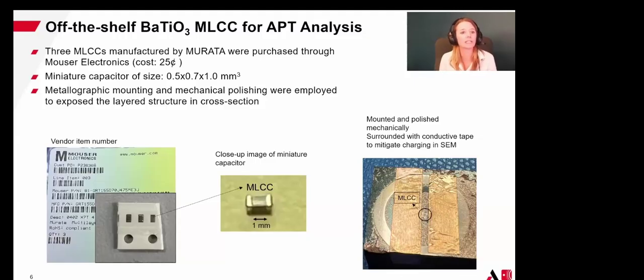What we've done here is actually put this in a metallographic mounting press. Here we're just using a copper washer to both hold it and provide a guide for where the bottom surface is. And we can mechanically polish that down so that the interior of that MLCC is actually visible to us on the surface of the SEM. Here we've also used a little bit of copper tape just to help things be more conductive, because if you've worked with metallographic mounts in the past, you may know that these are epoxy-based and not always super conductive in the SEM.